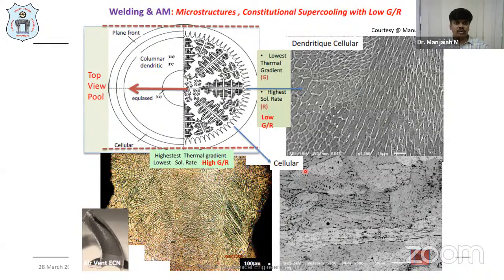And if you see how welding is related to the manufacturing process, the microstructure, and the constitutional supercooling with the low G by R ratio, that is the thermal gradients and the solidification rates. If you see, the solidification takes place from the outward to the inward. In the same fashion, in the manufactured components towards the build direction, the solidification takes place from the outward to the inward.